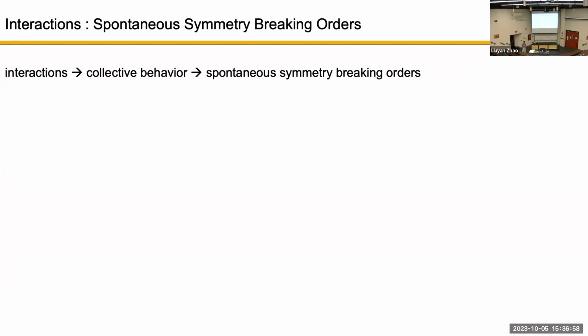So often in our measurements, we do not measure interactions directly. We actually measure the manifestation or the consequence of interactions. One type of manifestation of interaction is the formation of symmetry breaking phases. Your lattice has a particular symmetry, but because of interactions among electrons, or electrons and the lattice, or others, your electronic state or magnetic state has a different symmetry compared to your lattice. That is the so-called symmetry breaking arising due to the interactions.